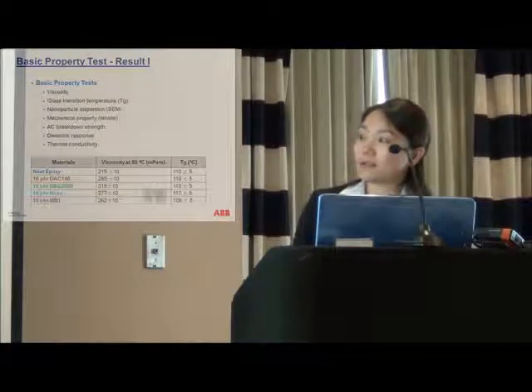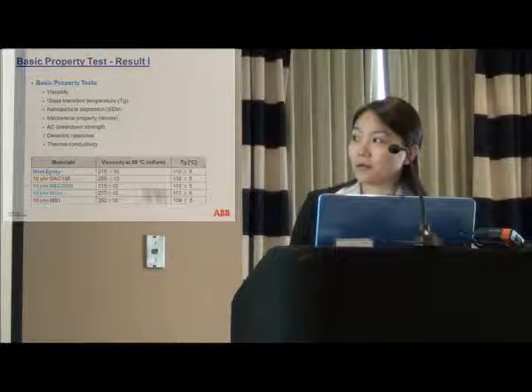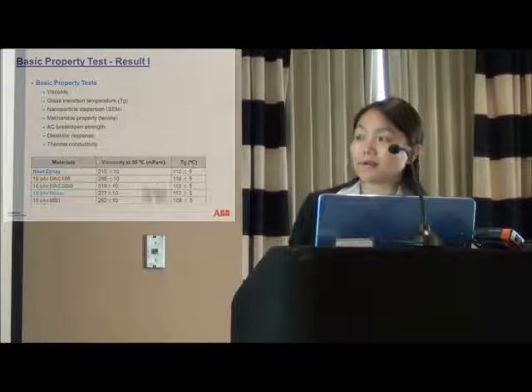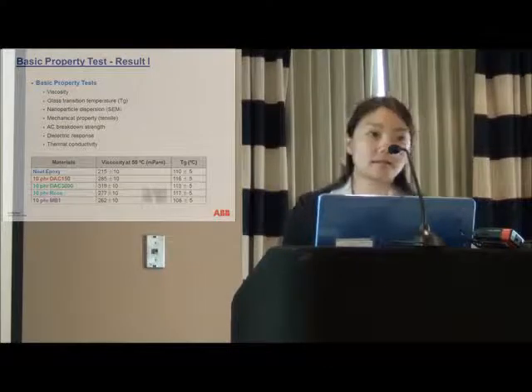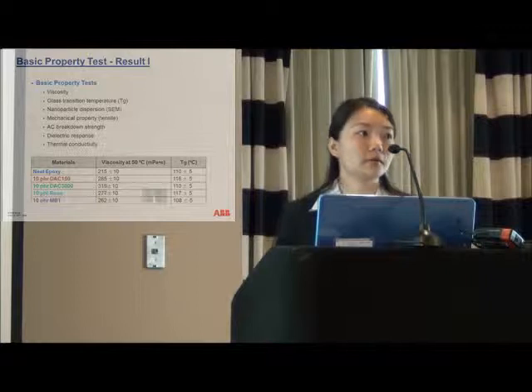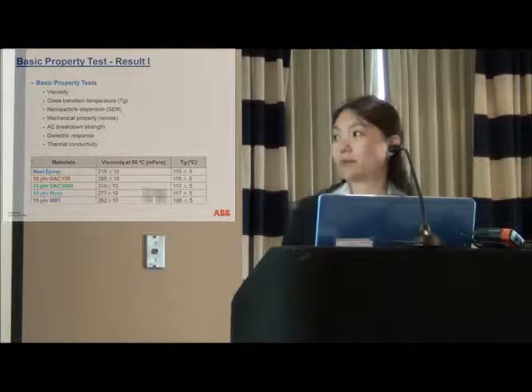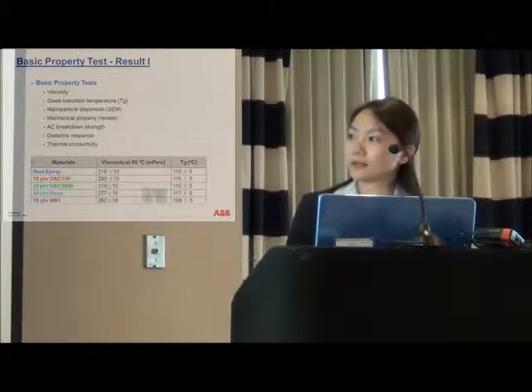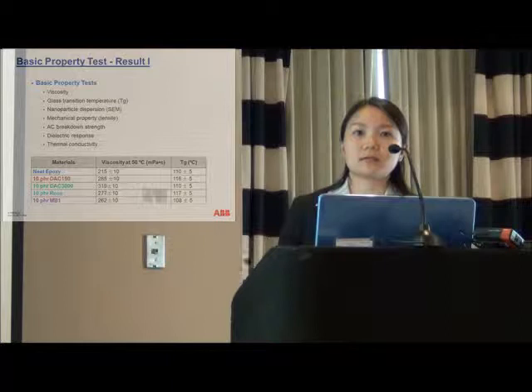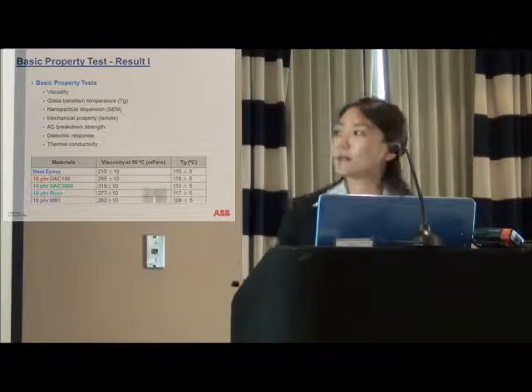If you compare the viscosity at 50 degrees, all the nanocomposites have higher viscosity compared to the neat polymer. That's reasonable since we add particles in there, but it's not significantly high that we cannot accept it.